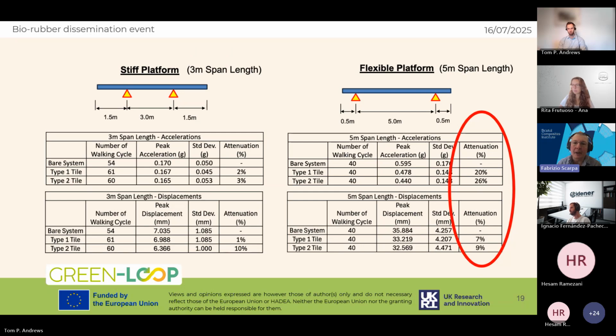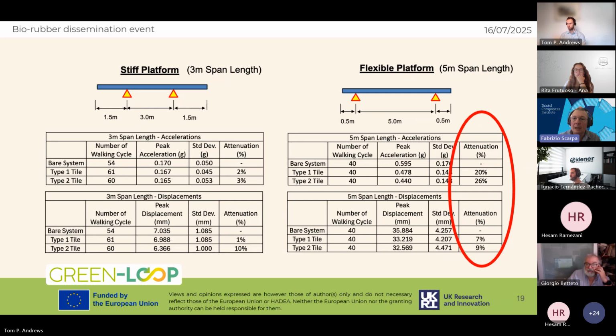I just want to draw your attention, on the flexible platform, to the significant increase of the attenuation of the response of the system when we put the two classes of rubber panels, both in terms of attenuation, but also when we consider the standard deviation for the displacement. So there is some indication that not only do the rubber panels provide a consistent attenuation to the response when people are walking on top, but also the presence of the lignin provides an added damping. And at the same time, it also added some stiffening because the peak displacements are reduced.